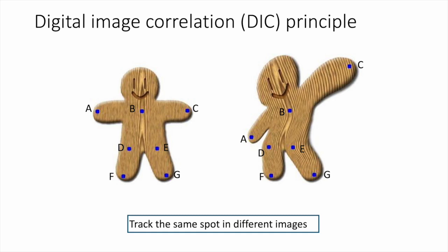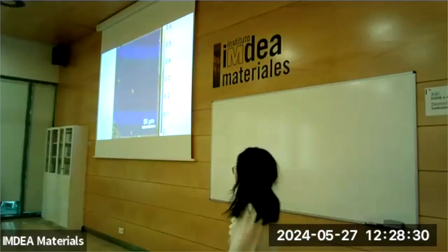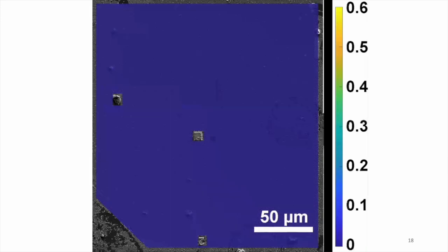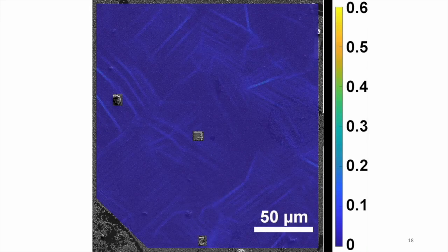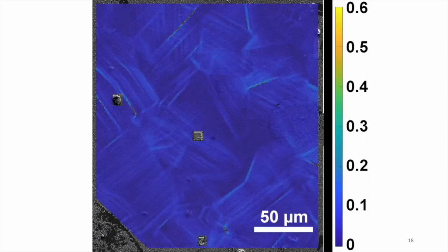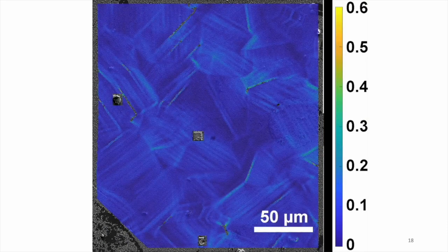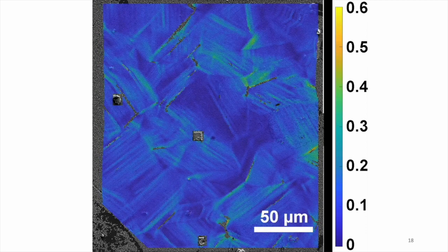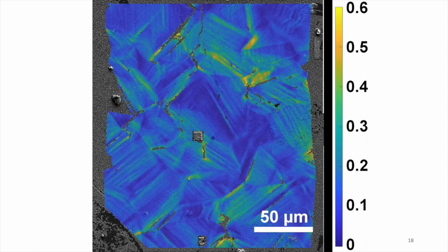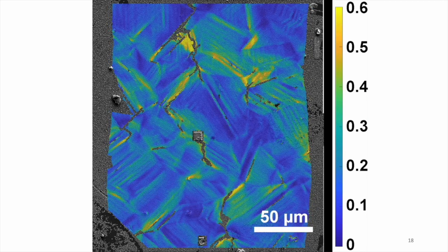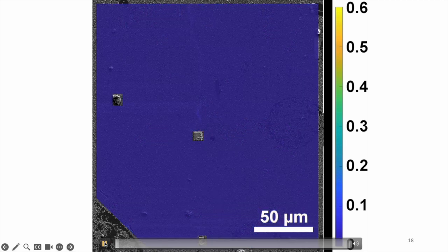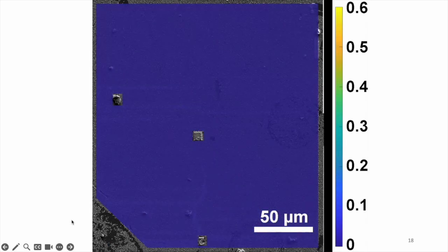And with this displacement, now we can calculate strain, right? So now let's take a look at what we got in the strain map. This is a 2D deviatoric strain map of the sample we tested, at the same location where you see the crack initiation. On this map, blue represents where you have low strain, and yellow is where you have high localized strain. As we do the testing, you see those areas without any color. Those are the places where our crack initiated. All right, let's replay this again.